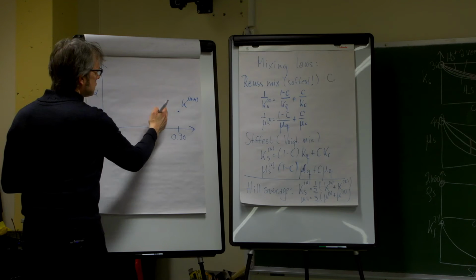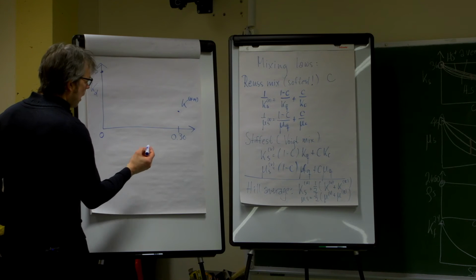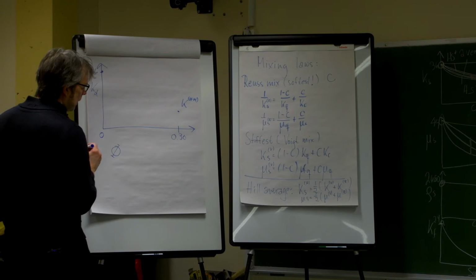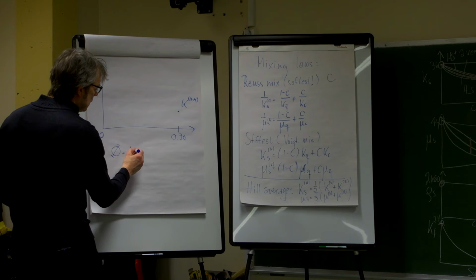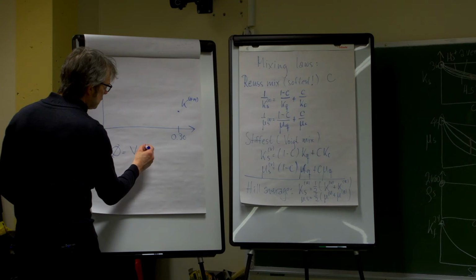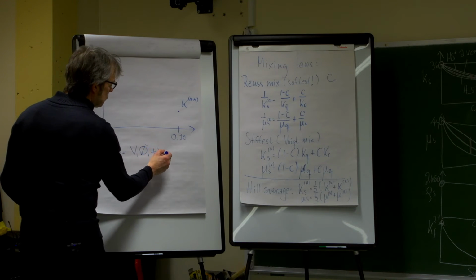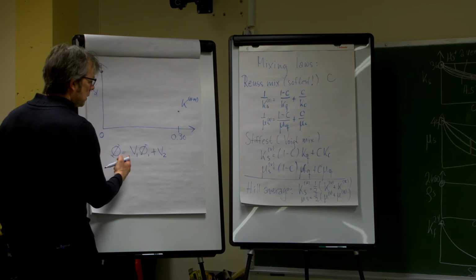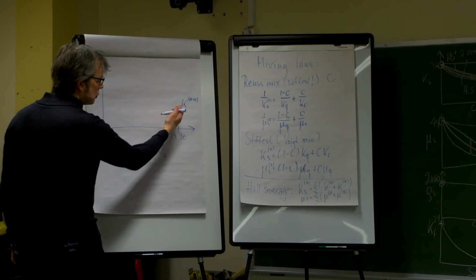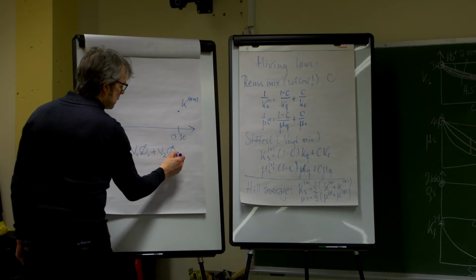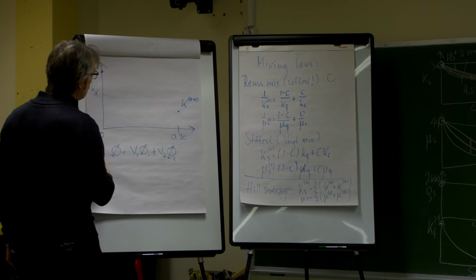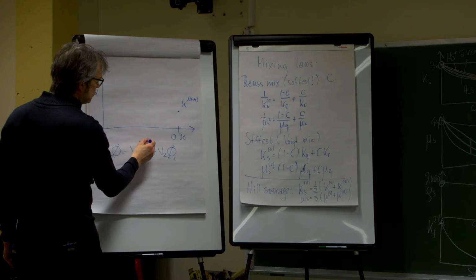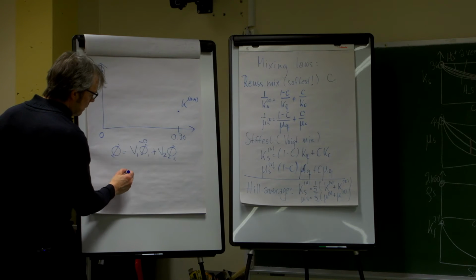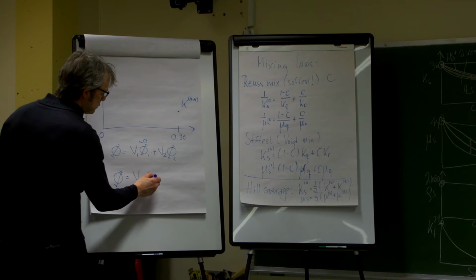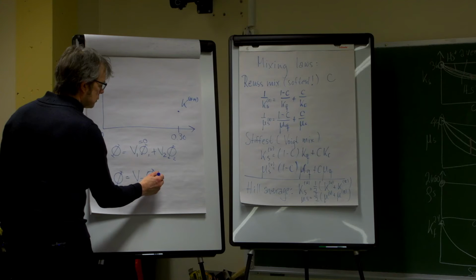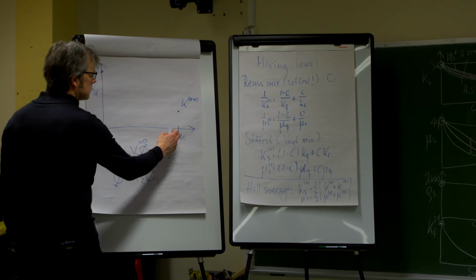So now I can start to mix these two. Let's just say, what is the porosity if you're mixing two end members here? If I have a volume fraction V1 of one material with porosity phi 1, and another material with volume fraction V2, which in our case would just be 1 minus V1, since we just have two components here, with porosity phi 2. So if I mix two end members, and of course this is simple because the porosity is 0 here, the total porosity is simply V2 times phi 2, which is 0.36 in this case. This is the end member.